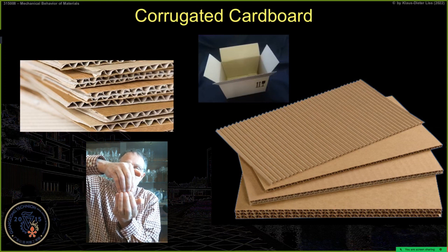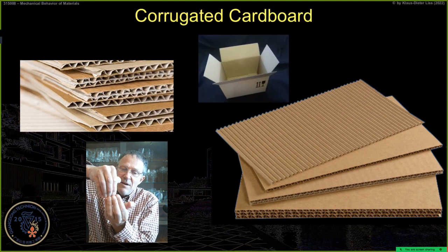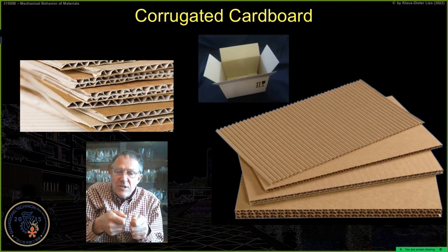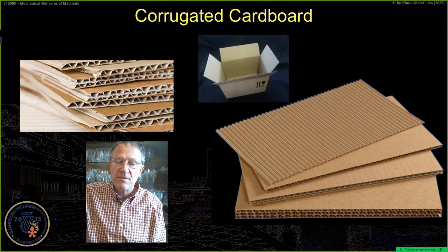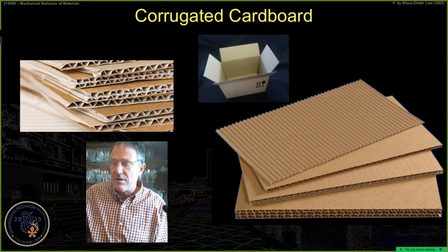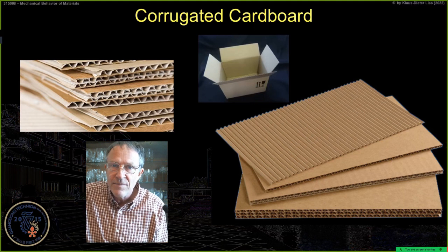Then you can do the experiment in your office, in your home, in your dorm, the 2 cardboards, and just displace it with a little normal force, displace it by 1 ripple, then you will see the shear force you need to overcome the ripples. Easy like that. That's a very simple model. But it doesn't work. We are wrong 2 to 4 orders of magnitude.